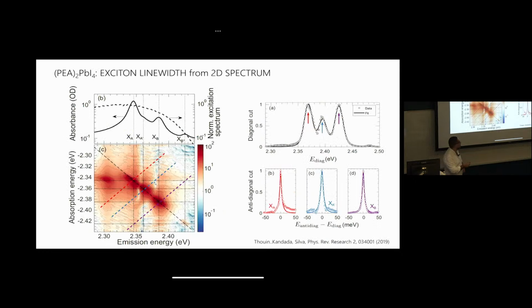So here's a measurement of this two-dimensional line shape. This is a much thinner sample than before. You see that these exciton resonances are much better defined. Here's one, here's XB. There's other things that we make out with this thinner, better resolved sample. But you see these peaks in this two-dimensional spectrum. Here in the diagonal, you see these features, as you should. You see that XA and XB have cross peaks.